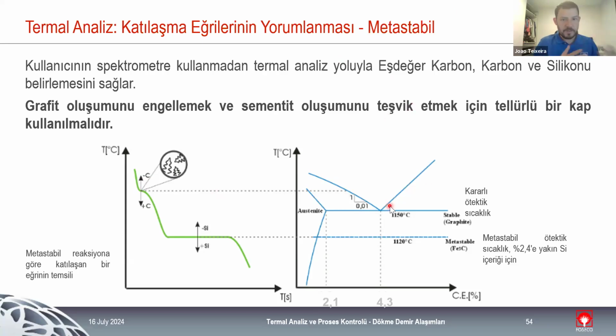We already discussed this, but in this part we have the graphics. But for metastable, so with the cups with tellurium, the main objective is to only know the carbon content and the silicon content. So we consume all the carbon in the sample. We don't allow the carbon to transform in graphite. So we have a straight line at the eutectic point, as you can see here. So we don't have any type of transformation affecting the readings of the system.